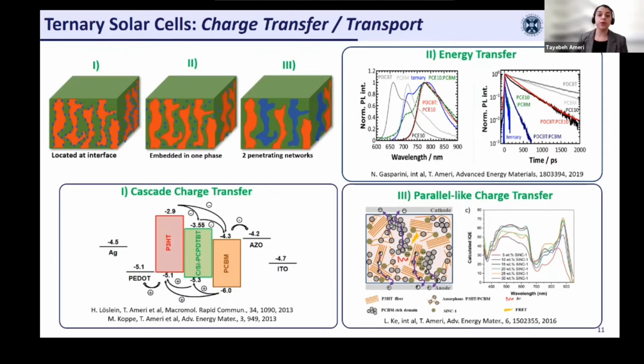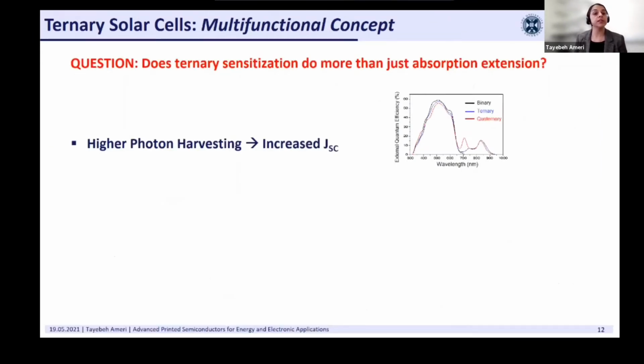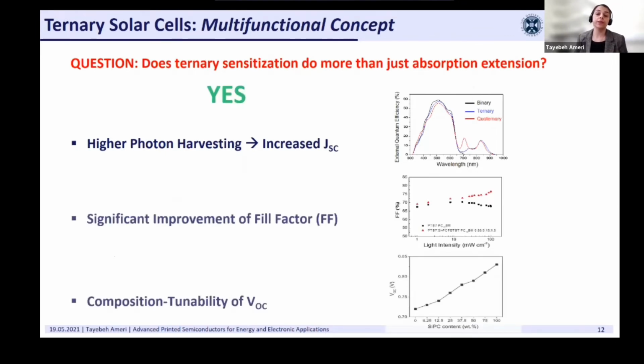The next question to ask was, does ternary sensitization do more than just absorption extension and increasing the short circuit current? The answer was fortunately yes. We learned over time that we may have a significant improvement of fill factor or even composition tunability of open circuit voltage by introducing the sensitizer. Here it was quite easy to understand what's going on. We have higher photon harvesting, and that's the reason we can improve the short circuit current.